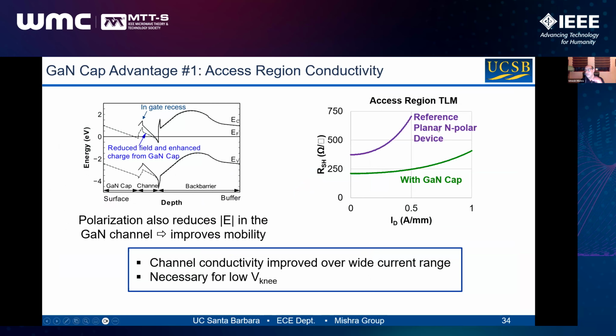Without the GaN cap, the access sheet resistance goes from 300 ohms per square, and with current, it goes up even higher to 700 ohms per square. That's too high. With a GaN cap, we can be below 250 ohms per square, and there is no current choke in the system when you put a GaN cap. This is a big deal.